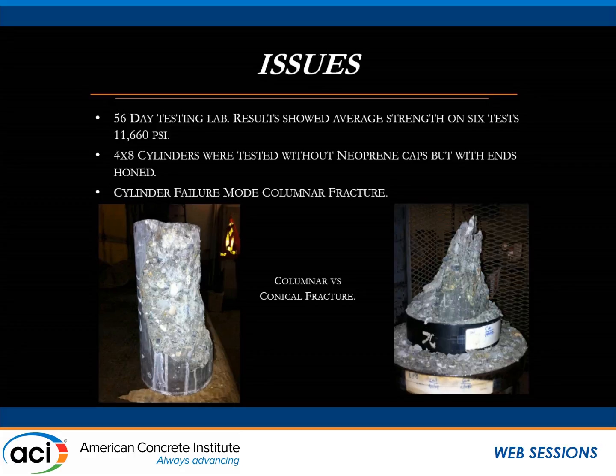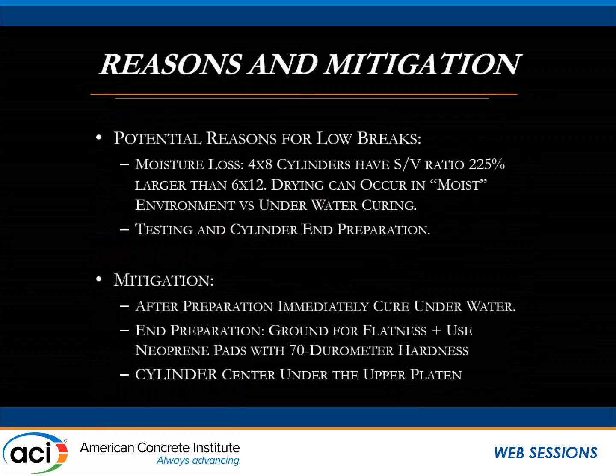And usually you go back and blame the mix designer, but the concrete mix designer on that job had a long history in high-strength concrete. We had a lot of confidence in them. So we decided to tweak the mix a little bit first. That's how we dropped the water-cement ratio a little bit. But then we started focusing on how these cylinders are tested and cured. So we got Professor Jansen involved in all this, and Jenny. Long story short, we started looking more into the potential reason why we were having these low breaks.